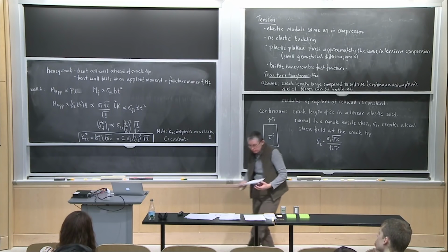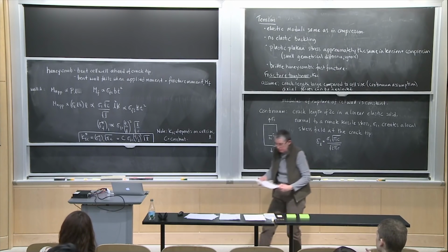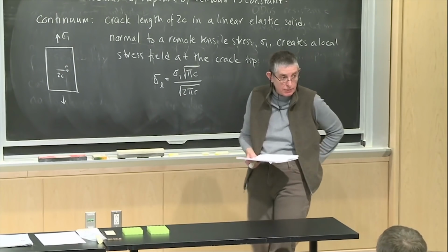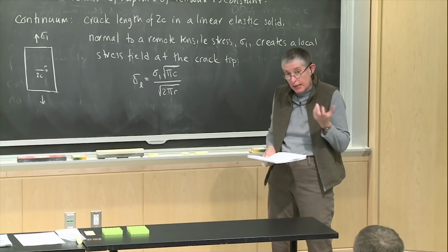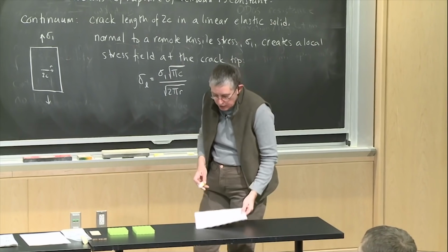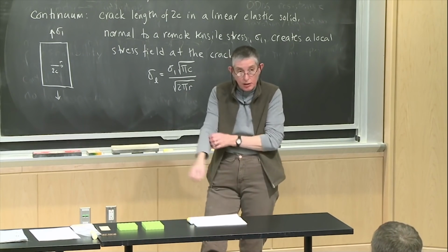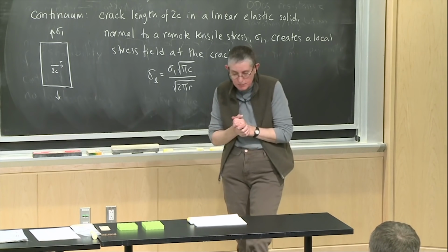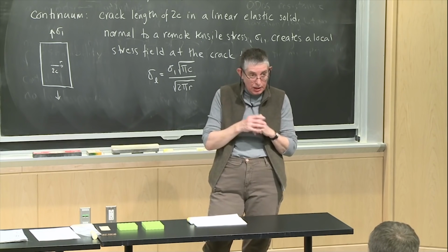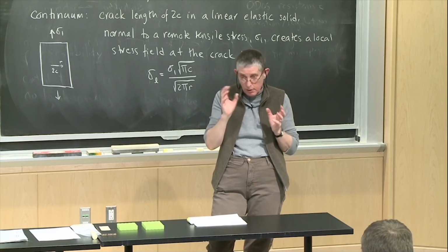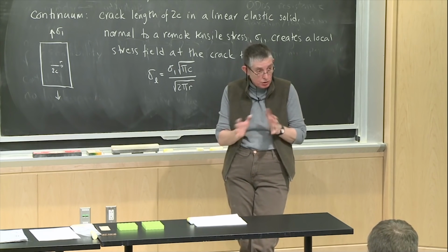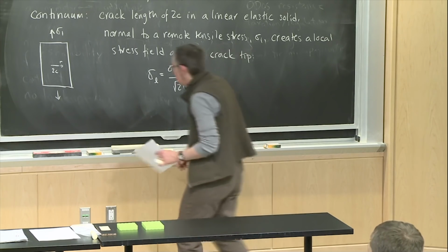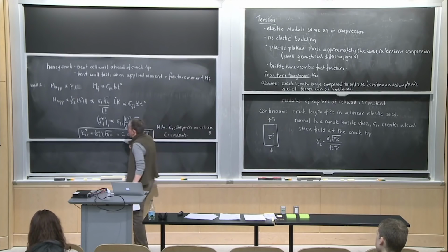So the next thing I wanted to do was talk a little bit about in-plane behavior, but for a different cell shape, for triangular honeycombs, because they deform by a different mechanism. And they can be used to represent the lattice materials that we looked at earlier, too. So if we have a triangular honeycomb with triangular cells, triangulated cells behave like a truss. And you can analyze trusses by just saying that the joints are pin-jointed. There's no moments at the end of the joints or end of the members, and the forces are all axial. And so the behavior is a little bit different. And so I wanted to just show you how these triangular honeycombs work, too.